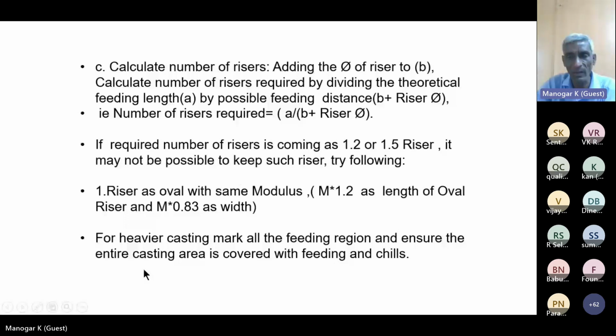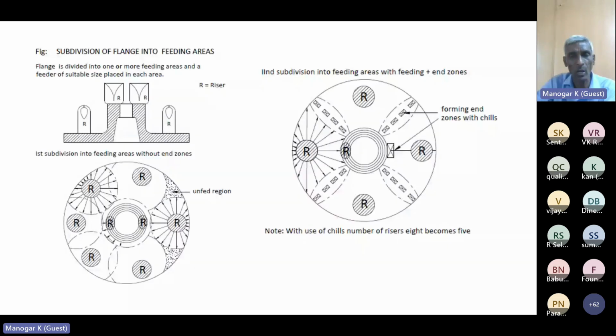For heavy castings, mark all the feeding regions and ensure the entire casting is covered with feeding and chills. Wherever the number of risers is coming, you have to plan for cut-off chills or use chills where the feeding region is not covered. You can follow like this. This is the example given. Without chills, the number of risers is more. When you use chills, the number of risers is reduced and it improves the yield.